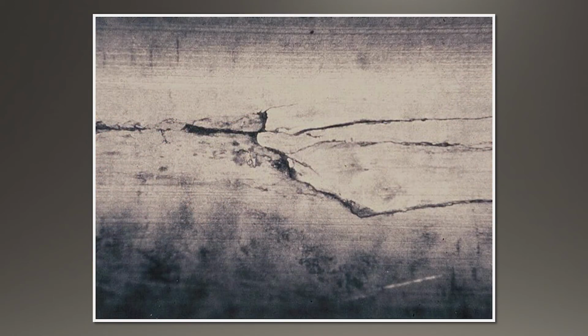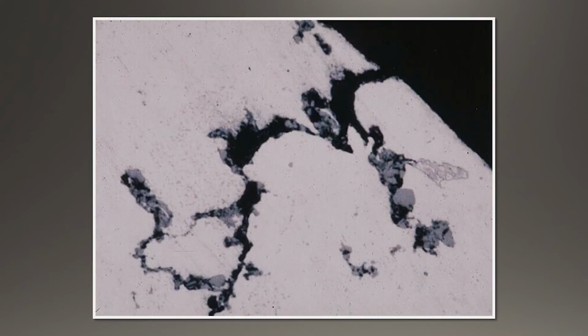This was on the rod with a crack, and if you look at a cross section of it in this picture, now you can see that the crack is very irregular, and that's because it took place at elevated temperatures at the grain boundaries, and since it was hot, it was exposed to the air and oxidation took place. So this is now probably a hot tear that was caused during casting, during solidification, in the process of making the casting bar.